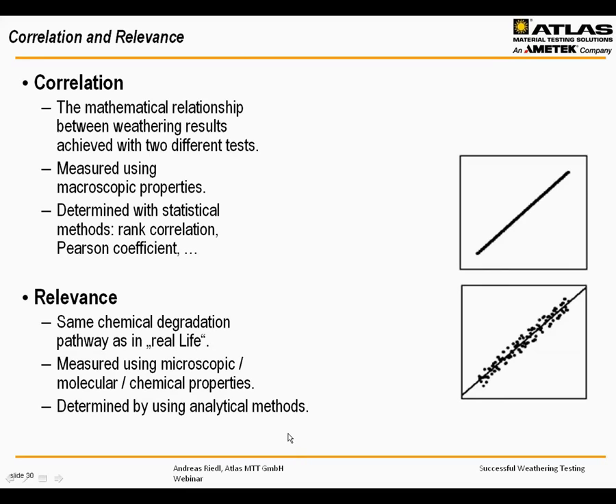In contrast to correlation, which looks at the macroscopic level, relevance looks at the microscopic level. We call a test relevant if the test induces a similar chemical degradation as in real life. That means the chemical reactions, the pathways, the critical photochemical products and so on should be the same as in real life. If this is not the case, then the test distorts the degradation mechanism and is not, in our terminology, relevant.